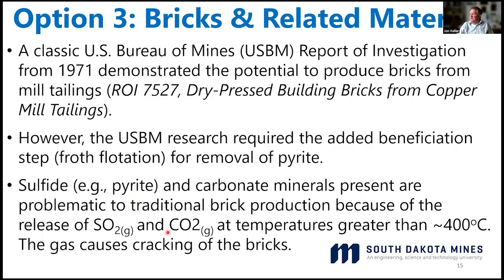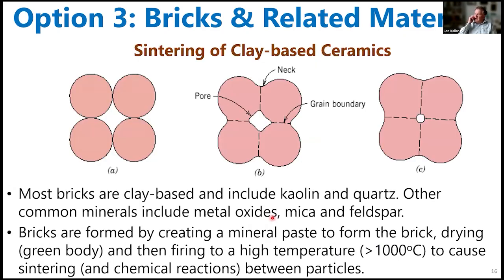And so with traditional brick production, you want to avoid SO2 and CO2 gas, and those come off at higher temperatures. SO2, obviously, is a bad actor, but those gases will cause cracking of the bricks, and since they're structural materials, that can't be tolerated. So what happens with brick making? Most bricks are made out of clay-based materials, and that means they'll include clay minerals like kaolin that I mentioned earlier, and for sure quartz. Other common minerals in clays or clay-based ceramics include metal oxides, mica, feldspar, and the brick is formed by creating a mineral paste to shape the brick.